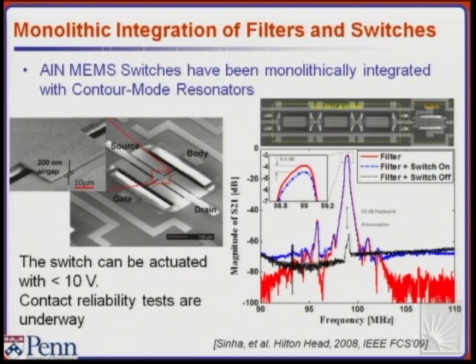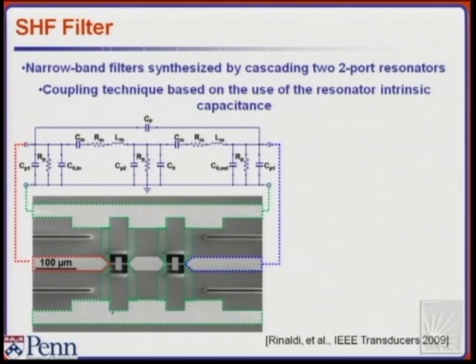And we've actually monolithically integrated it with the MEMS filter, and you can see that we can really turn our filter on and off, with more than 50 dB of rejection from the on state to the off state. And that's done all on the same chip. But as I said, it's all about going to higher frequency and miniaturization.